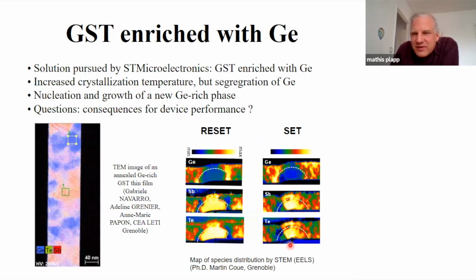And what you see is after memory operation, actually you have a redistribution of the components. So for example, in this active region that is delimited by the white dashed line approximately, you see that the concentration of germanium has diminished because here blue corresponds to a low concentration, whereas the one of the other components has increased. Clearly, the memory operation changes the composition of the material. And the question is, what are the consequences of this for the memory working?